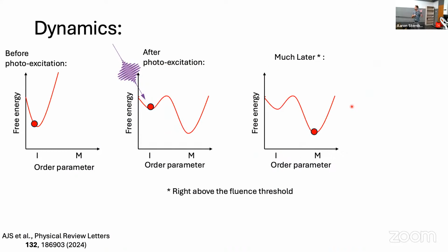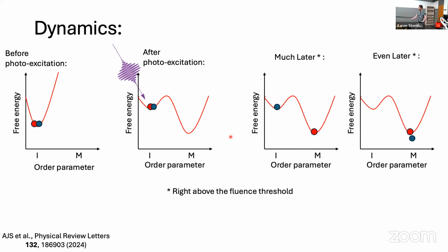So to summarize, what does this actually tell us about vanadium dioxide and the transition? We have a situation where the system starts in an insulating state, and then after we photoexcite it, the metallic phase becomes preferable. The system can gain bulk energy by transitioning into a metallic phase. However, it takes a long time before the system actually will evolve into this metallic state. At a neighboring location, what we are seeing is that the system actually takes even more time to evolve into the metallic state. The reasons for that are